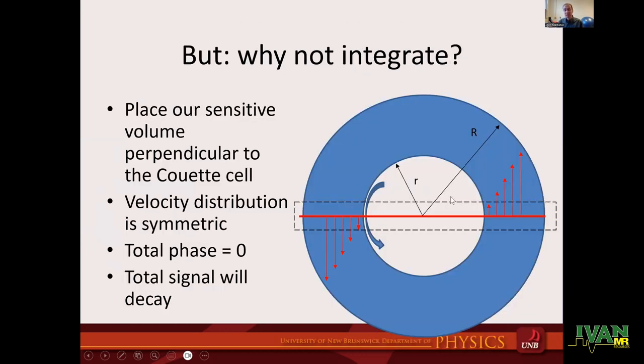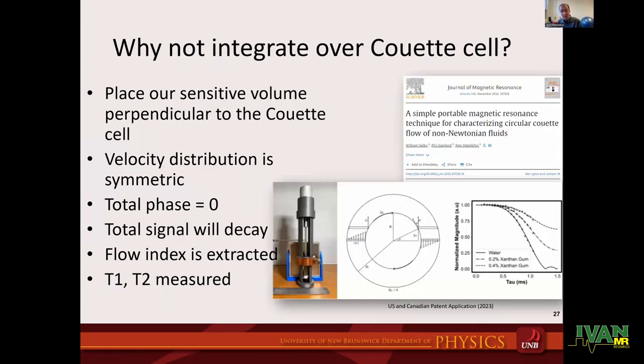But imagine you have this Couette cell, and we're looking at it from above. What if you just integrate over the whole volume, like shown here? You have a distribution to the right and a distribution to the left, so the total phase when you add all these signals together will be zero. But the signal magnitude will decay in a well-defined way. That's exactly what we did. We built this apparatus: this is our Couette cell inside, and the magnet array over there is the whole setup. Then we observe how the signal decays, and we can extract the flow index from those decay curves. They work quite well.